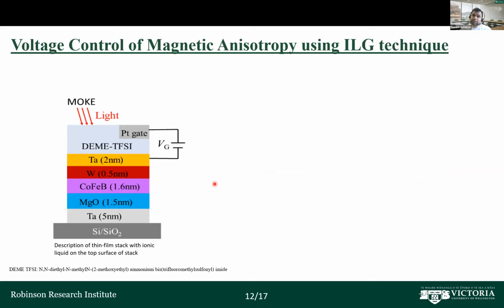For this experiment, we mostly used this thin film stack, which consists of tantalum, MgO, and a thin layer of CoFeB, 1.6 nanometer. We used a heavy metal, tungsten, to induce a perpendicular anisotropy, and then we capped it with tantalum 2 nanometer. On top of this, we drop an ionic liquid, that is DEME-TFSI. So this is a long name, but anyway, the purpose is that we then apply the voltage on top of the thin film layer and the ionic liquid. We apply the voltage and see how the magnetic anisotropy changes.